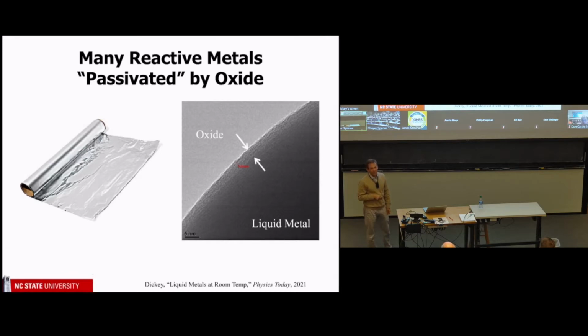Well, the reason you can safely have it in your kitchen is because it does react with the air and forms an oxide, and that oxide protects the metal from additional reactions. Without that, it would just get chewed up, and we wouldn't have aluminum in our society. So this is what it looks like. If you do a cross-sectional view, here's this oxide layer, which is only about 3 nanometers thick. So it's only a few molecules thick.